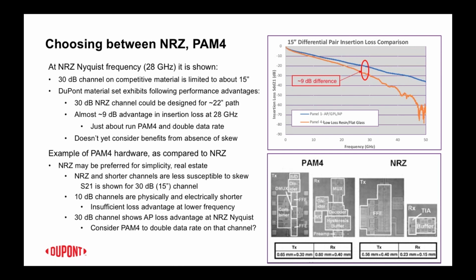Why you might not use it, again, in the bottom right shows PAM4 hardware is a little bit more complex and takes up a little bit more real estate. These are some of the reasons why it's used for some of the longer channels, but not as often for some of the shorter channels. As well, for the 10 dB channel, it's hard to back that up in frequency enough to get to where the half frequency is not going to have 10 dB less insertion loss. So it's going to be a more useful technique in the physically longer channels.